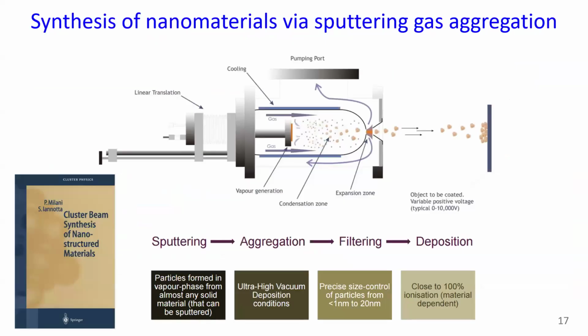synthesis, the way we're addressing this challenge is by exploring different synthetic routes. And here we're borrowing from vacuum phase physical chemistry and high vacuum surface science. Specifically, we're using a technique called cluster beam synthesis, which is analogous to conventional sputtering. For example, if you're making samples for SEM prep where you sputter a metal to deposit a thin film on your surface in order to make it conducting. Similar idea, however, once the elements are sputtered in the gas phase, you introduce a carrier gas that cools the atomic vapor to condense into nanoparticles, and then you can deposit a beam of nanoparticles onto your catalyst surface.